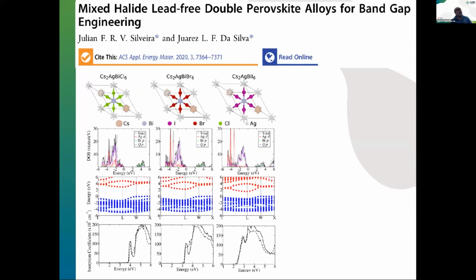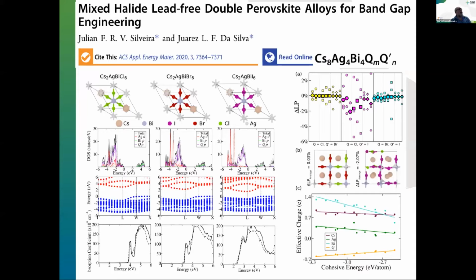We now move to the double perovskite systems. In this case, we consider the systems combining cesium, silver, bismuth, and chlorine, bromine or iodine. The idea here is the following: can I mix the halides in a way that improves stability or compromises it? Because, as you saw before, chlorine has the highest cohesive energy and the highest stability, but the band gap is reduced in the direction of iodine. We take those systems and perform a large number of calculations to identify how they make the alloy, and then you create the double perovskite structures.